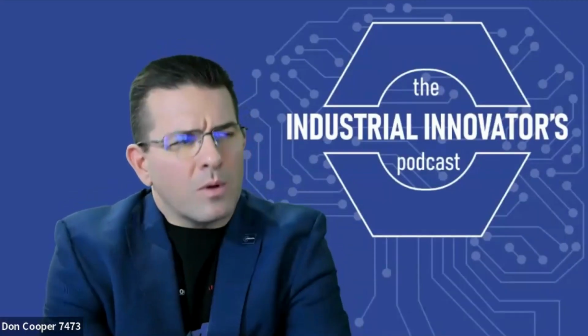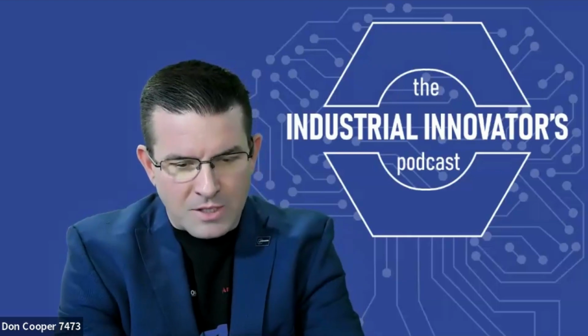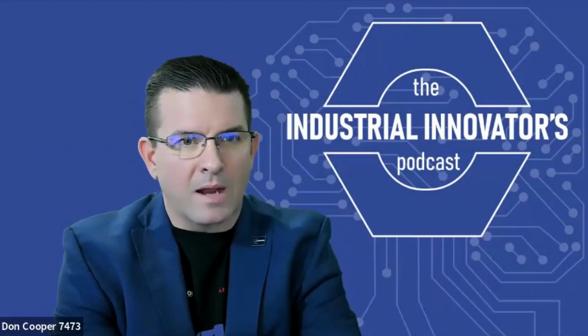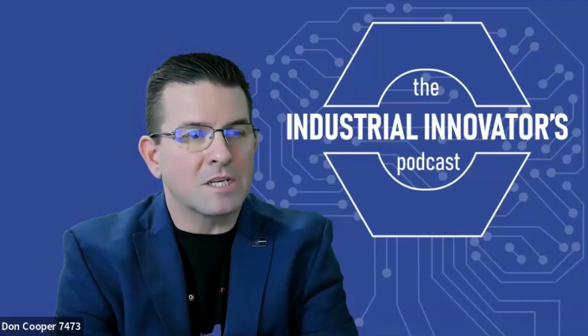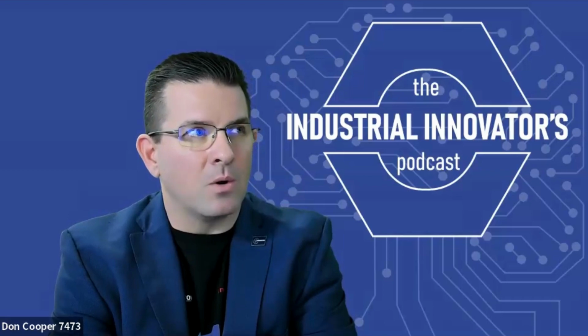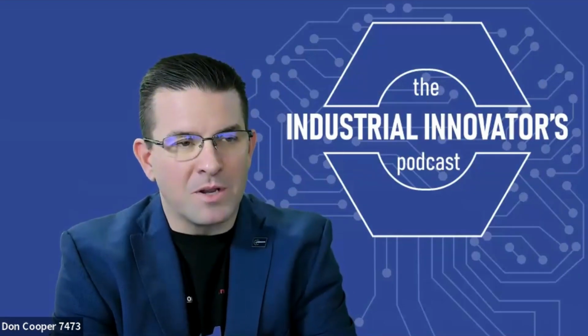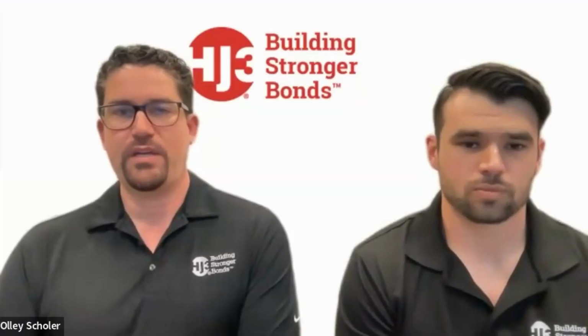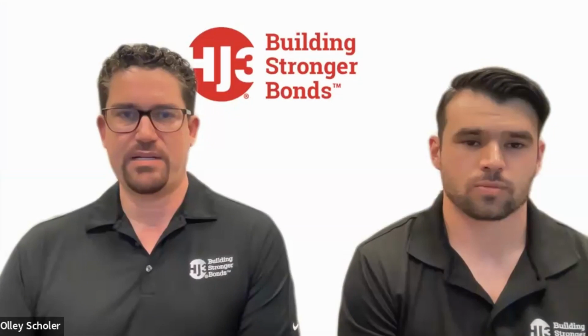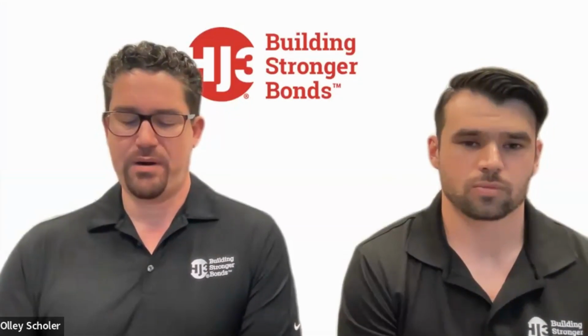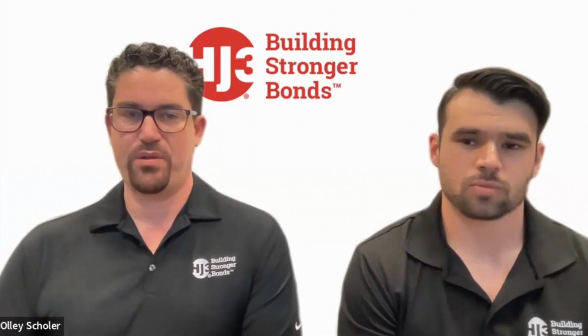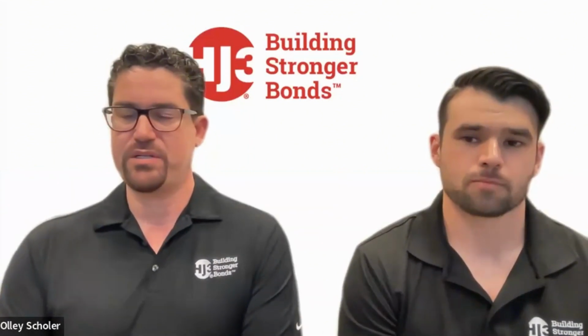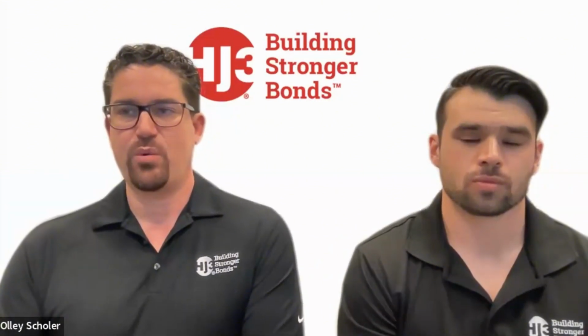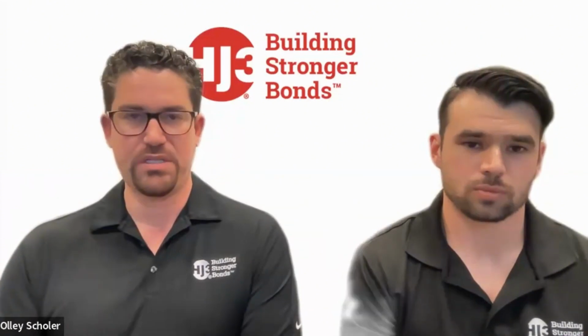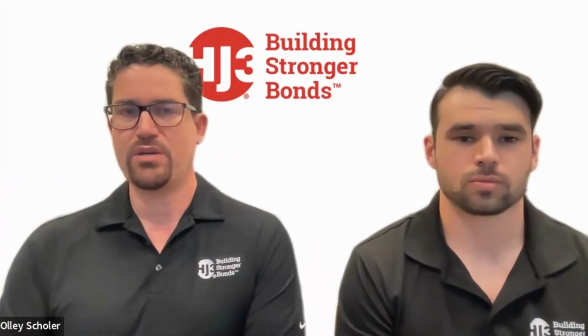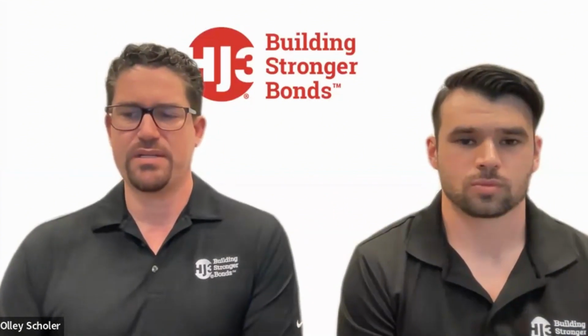Right. So with that reduction factor, I'm just trying to understand its impact. So will that impact the life expectancy of the repair, and or does it impact the amount of material that you have to use, or is it both? It's going to be both. Any system that's selected, part of the design criteria is to compare the surface temperature, the chemistry with your long-term testing. And some chemistries and temperatures are just not compatible with composites. So you want to look at how your testing is in, just immersion, looking at coupons and samples, but also how it retains strength. So those are considerations on selecting the system.